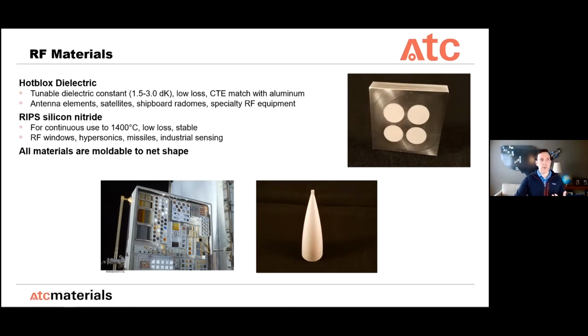So versus some traditional or alternate materials where the aluminum might be honed, the material might be machined to fit, and then it's pressed in there, we can just take the aluminum, mold our material directly into it, and it's ready to go. It also then is going to maintain that interference fit throughout any temperature cycles, so it's not going to crack if it gets cold, and it's not going to fall out if it gets hot. This is a great application for the material. We've also manufactured some different hemispheres and radome shapes, from baseball, softball size, things like that.